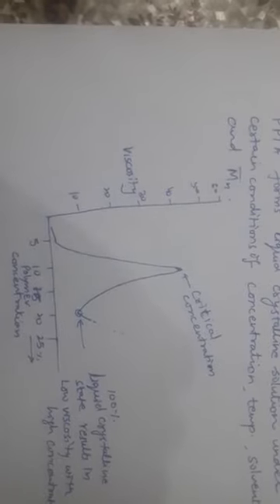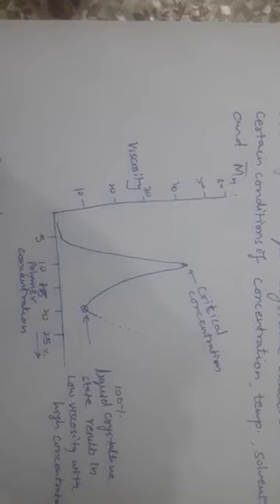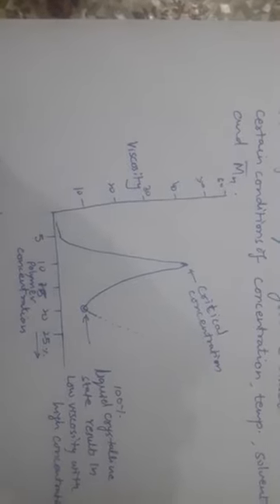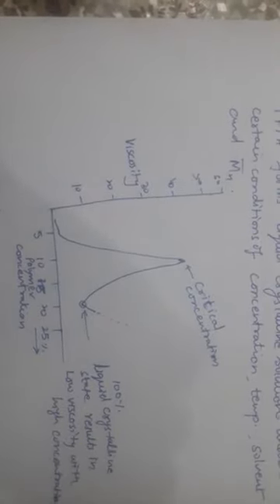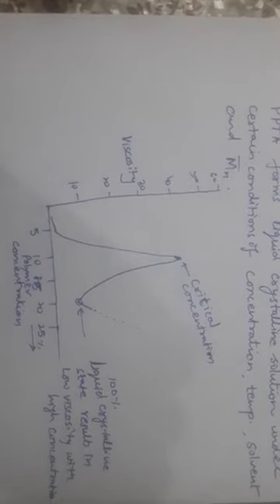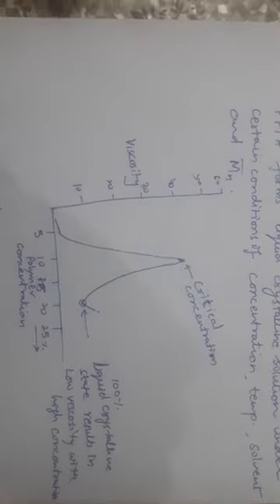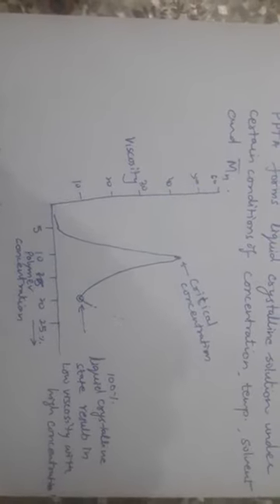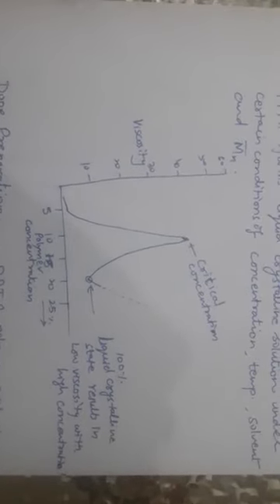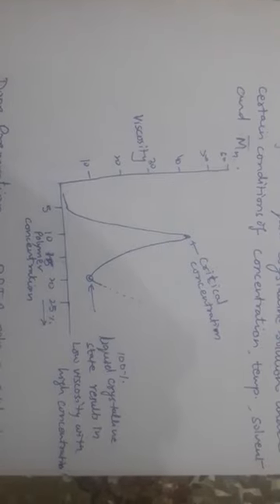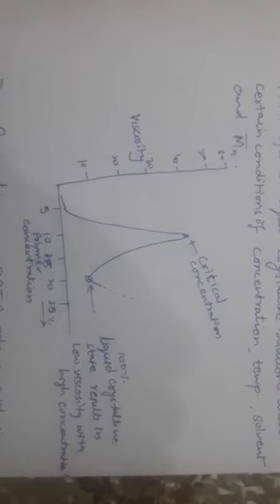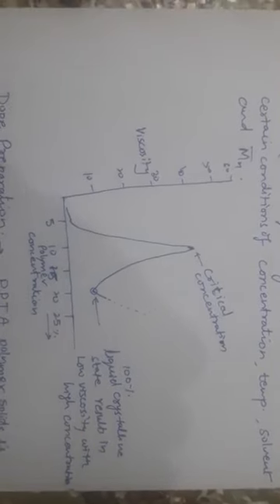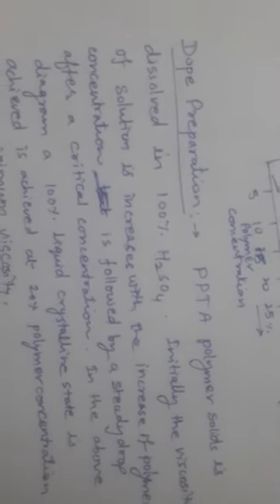At a particular critical concentration, in this diagram about 13 to 15% polymer concentration, it reaches the maximum viscosity. Further adding polymer solids to the solution, a steady drop in viscosity is measured, and it reaches its lowest value with a maximum crystalline state, the nematic liquid crystalline state, almost 100%, at a 20% polymer concentration in H2SO4 for PPTA type polymers. You can see this in the diagram. The dope can be prepared in sulfuric acid, 100% sulfuric acid can be used for this.